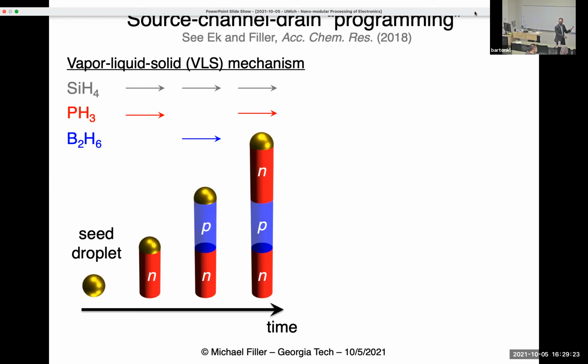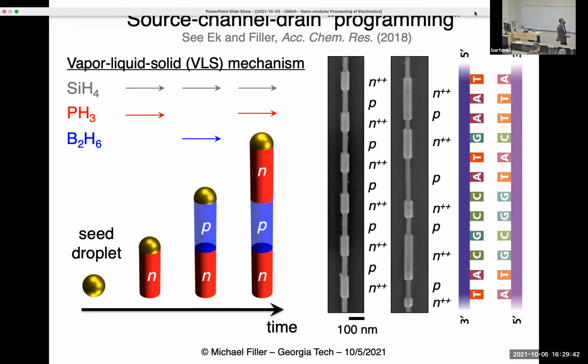It's a lot higher temperature than sugar and water, of course. This is on the order of 500 degrees C where this happens. And then the cool thing about this process is we can switch between different dopant precursors, phosphine and diborane, giving us N and P-type doping in that silicon as we grow the structure. And we're pretty good at doing this.